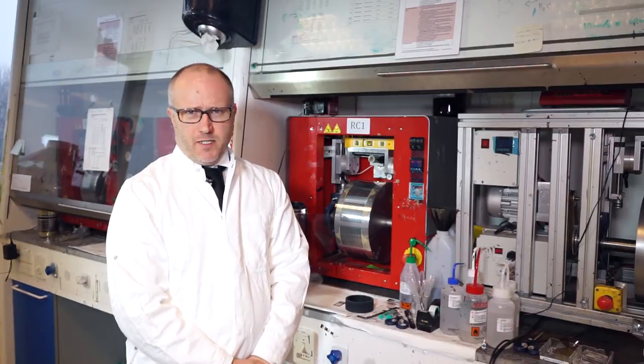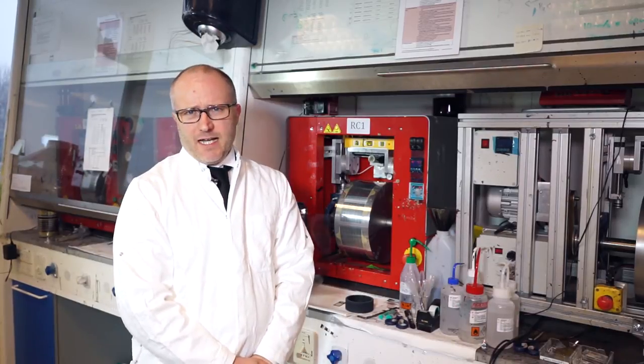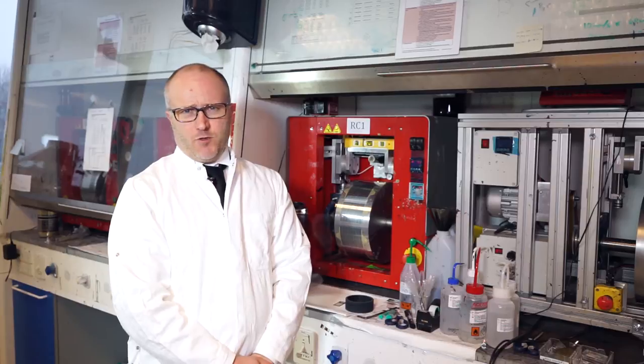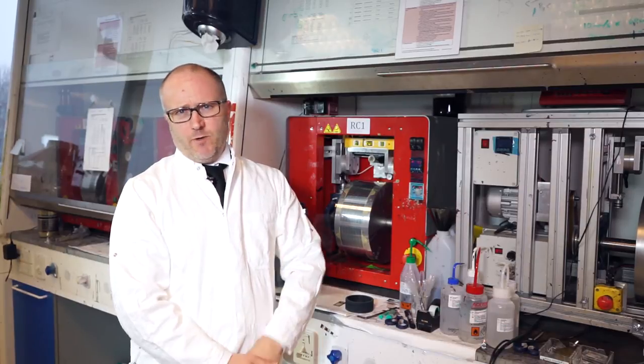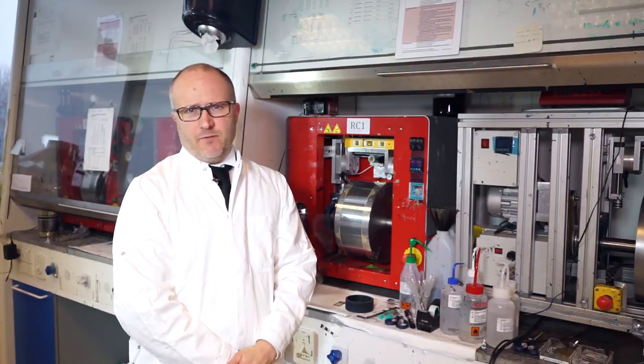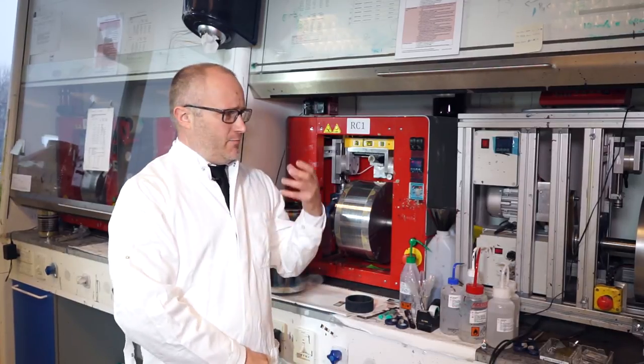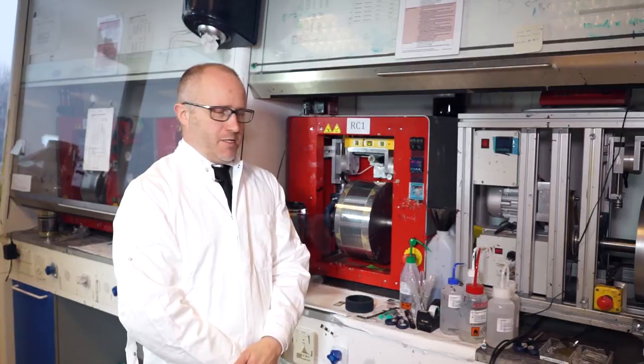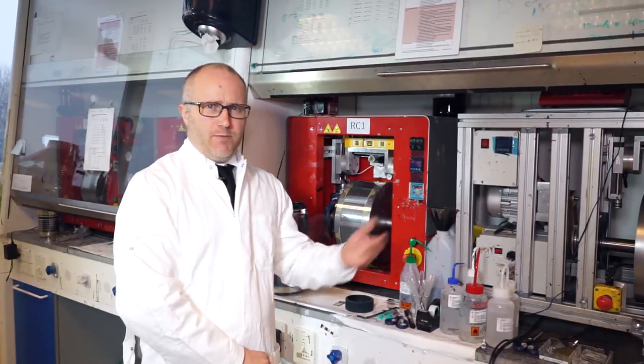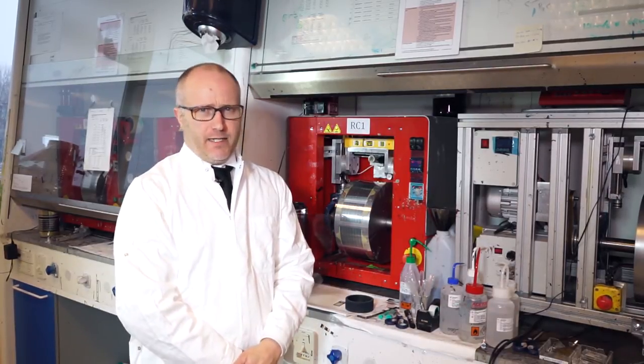In terms of processing time, the mini roll coater is similar or maybe slightly faster than spin coating, where typically you need a high vacuum evaporation step of a metal electrode or an oxide layer. And for the mini roll coater, on the scale of 1 to 2 hours, you can make a complete device stack, including the back electrode.